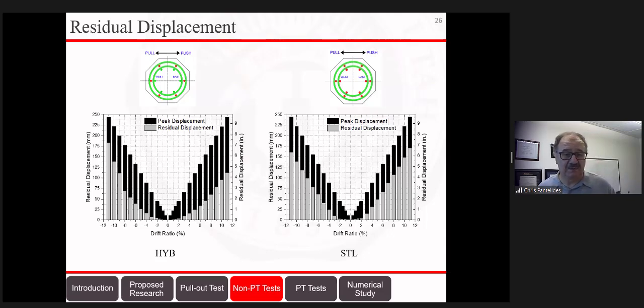So how about the residual displacement? Remember, these columns were non-post-tensioned. So even without post-tensioning, the black line shows you the peak applied displacement, and the white line shows you how much was the residual. So for example, at 10% drift ratio, the residual was about 3 inches, 3.5 inches. On the left, you see the hybrid, and you can see the hybrid has actually a little better performance than the one on the right, which is the steel. We expected that because the longitudinal bars of the hybrid column are elastic. So when you have something elastic, if it doesn't break, it will come back. It will tend to recenter.